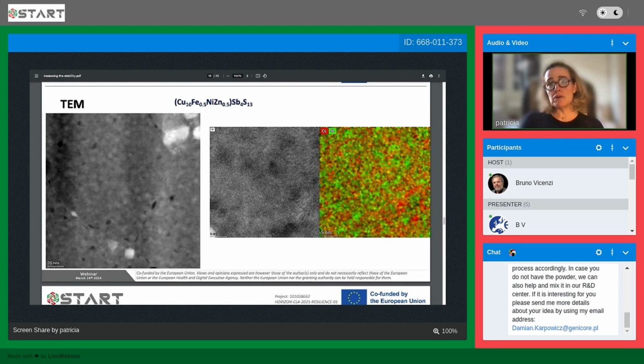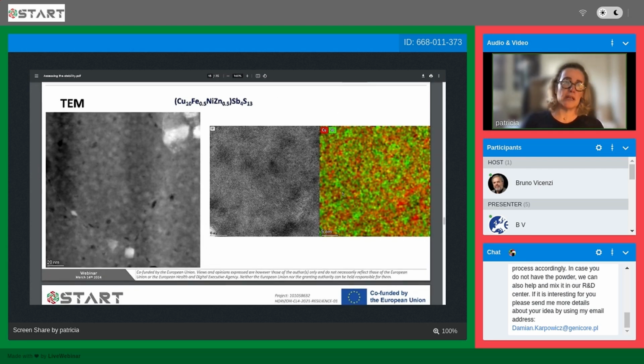And when we look at it with EDX in this case, we see some regions which are a little bit more enriched in antimony, and other regions which are a little bit more enriched in copper. And this means that we probably have the composition of two different types of tetrahedrites at a very, very fine scale, which might be interesting for the ZT, but we are still not sure. We are still investigating this.